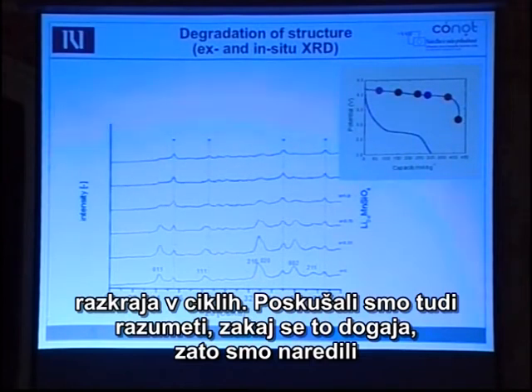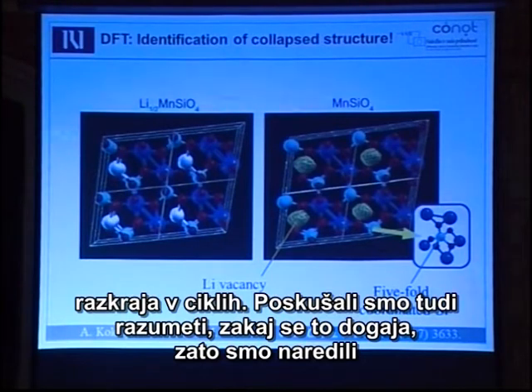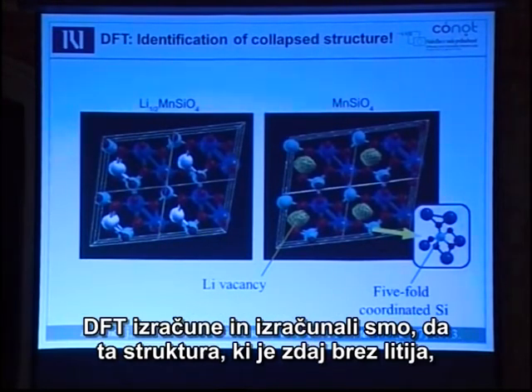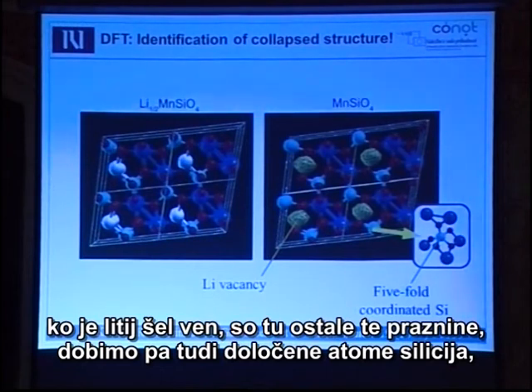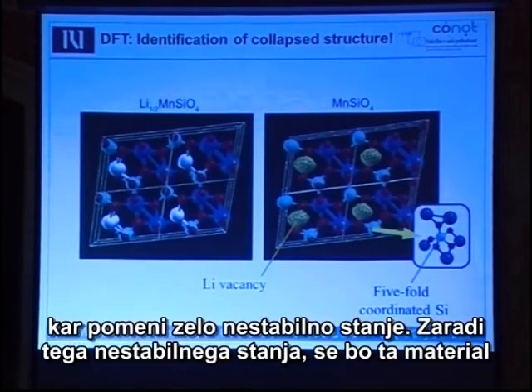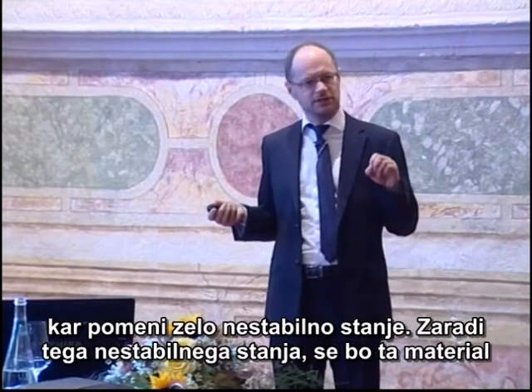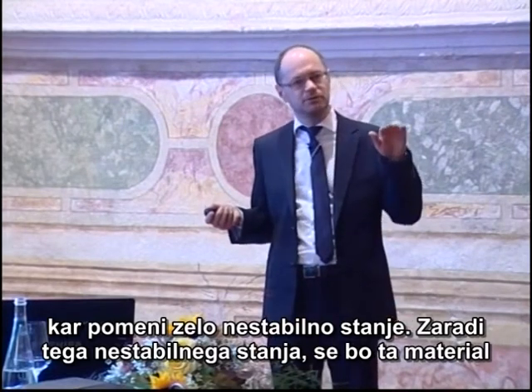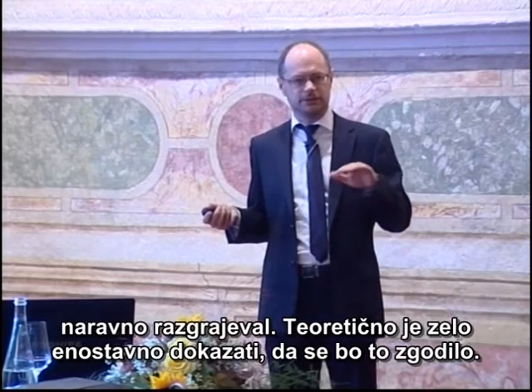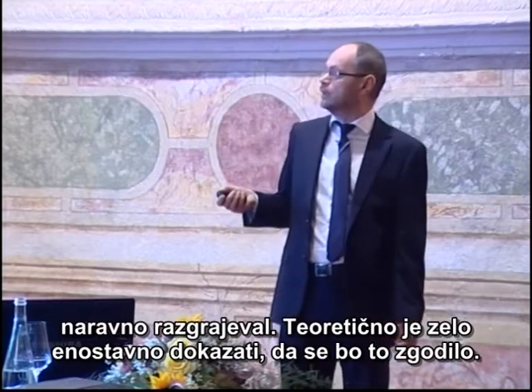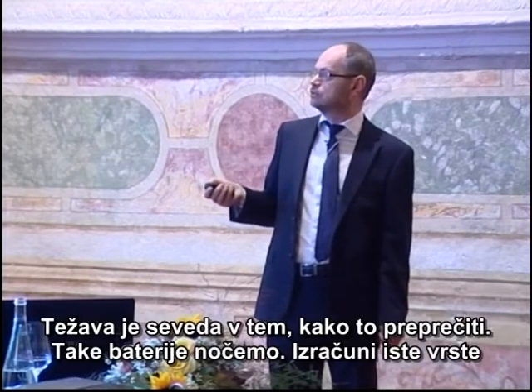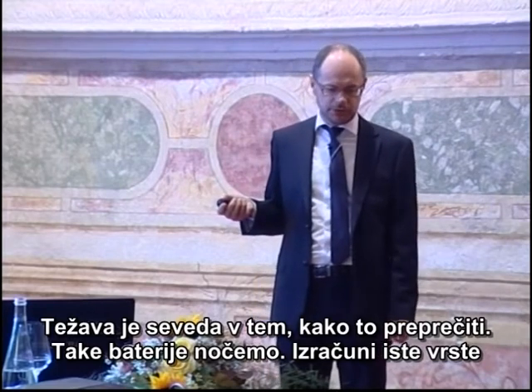We also tried to understand why this happens, so we made DFT calculations. This means ab initio calculations, and we calculated that in this structure, where it is empty of lithium, when you take lithium outside, you have these voids here, and you get certain 5-fold coordinated silicon, which is a very unstable situation. So due to this unstable situation, this material will degrade naturally. It's easy to show theoretically that this will happen. Of course, now the problem is how to prevent this, because we don't want to have such a battery.